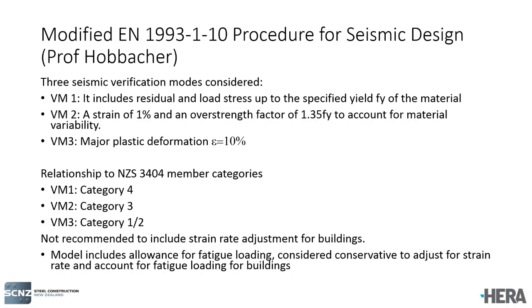Verification model 2 includes a minimum strain of 1%. Let's say the steel goes into yielding at this stage, and the load of 1.35 times yield point. So basically, in model 2, we can see the overstrength of the steel to account for any material's variability. So this is an overstrength factor. And the verification model 3 considers major plastic deformation in the steel of 10%, right? In terms of relationship between verification models and seismic member categories, verification model 1 is recommended for member category 4, verification model 2 for category 3, and category 1 or 2 should be dealt with using verification model 3.